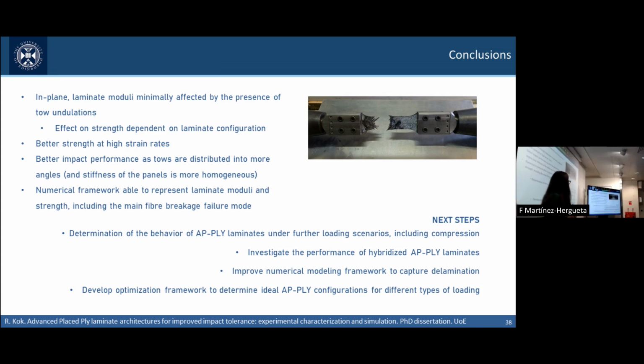So as a summary, we evaluated the mechanical response of different AP-PLY laminates, and we shed some light on the main deformation micromechanisms. We found that the response is slightly better at high strain rates, mainly because the undulations can act as crack arrestors effectively. That will end up in lower delaminations when subjected to through-thickness impact, with a better stability in the compression after impact response.